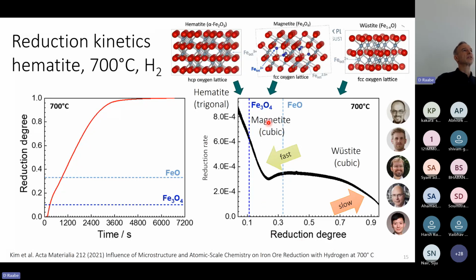And when we start with the trigonal hematite, Fe2O3, you can appreciate that the first step in the reduction is very fast, going into the cubic inverse spinel magnetite very rapidly. But when you are then in the cubic magnetite and transform further to FeO, which is likewise cubic, and they are sharing the same oxygen sublattice, then you lose reaction rate. And when the wüstite, which is gradually forming here out of the magnetite, in part at this temperature even out of the hematite, as we can find, you lose nearly 1 order of magnitude in reduction rate before you finally arrive at alpha iron. So that is kind of a challenge.